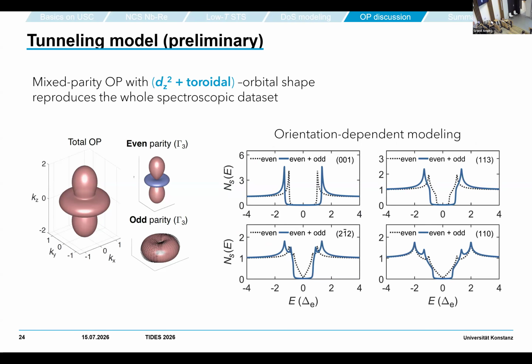When you do this, we can calculate, by superposition of the dz-squared and the toroidal orbital, what spectra we would expect for the different planes: 001, 113, 2-1-2, 110. Here you see we basically get the shapes also seen in the experiments—fully gapped ones, or ones with kinks in the slope, and also double peaks with coherence peaks appearing at twice the gap.